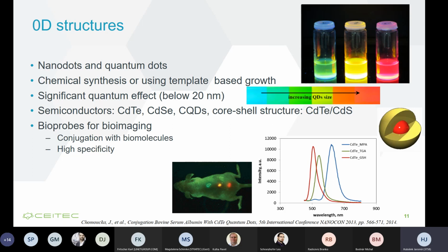As well, we deal with core-shell structures, which are more stable. Some stabilization can be done with the modification of the quantum dots, as you can see here. There is also some significant shift in wavelengths according to modification, which also helps to stabilize the quantum dots and helps for the bioprobe formation. Because these quantum dots are mostly used for bioprobes, for bioimaging, the surface of these nanodots has to be modified or conjugated with biomolecules with high specificity. Then they can be used, for example, to observe exactly the cancer with high specificity, as you can see on this mouse.